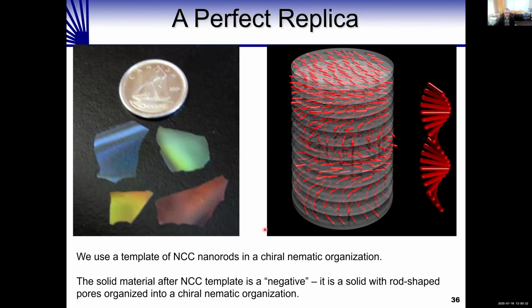So what we've been able to do is use cellulose nanocrystals as a template for chiral nematic organization. The solid material we get after using the cellulose nanocrystal template is the negative of it—a solid with rod-shaped pores that are organized into this helical structure.